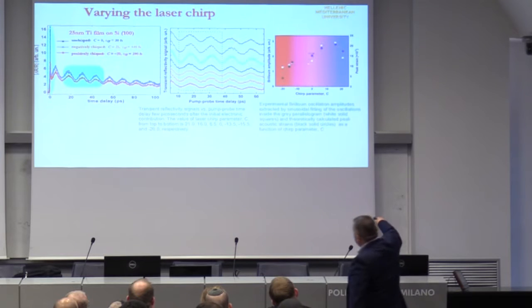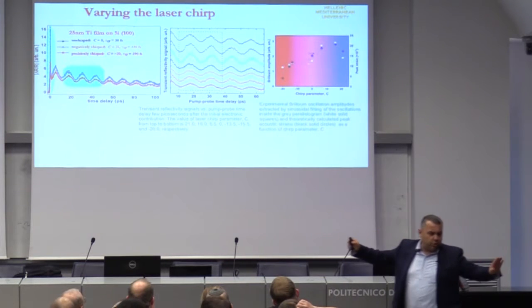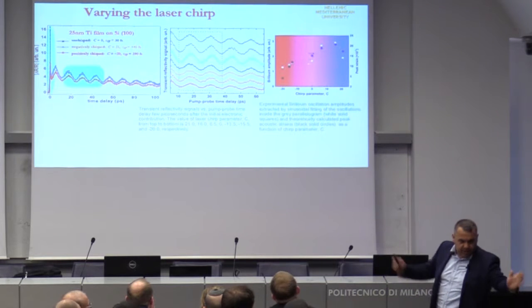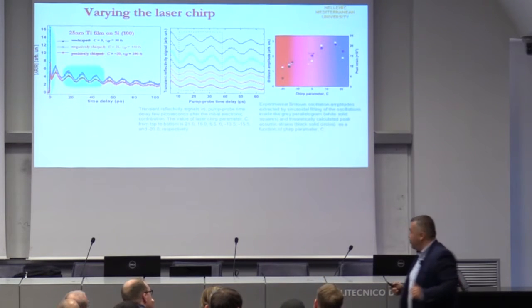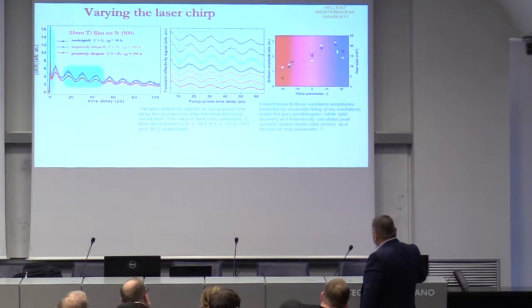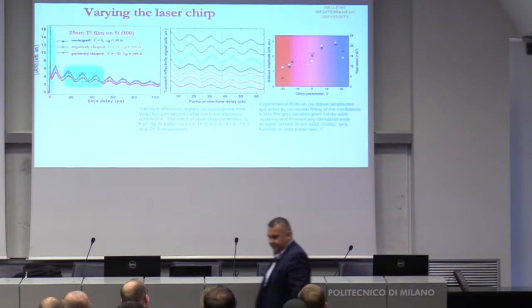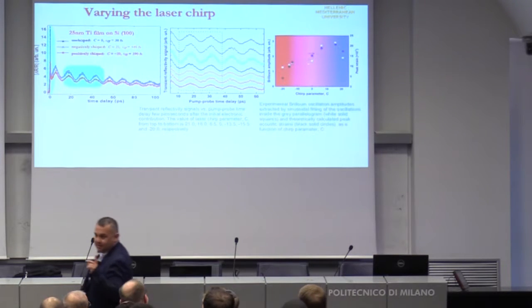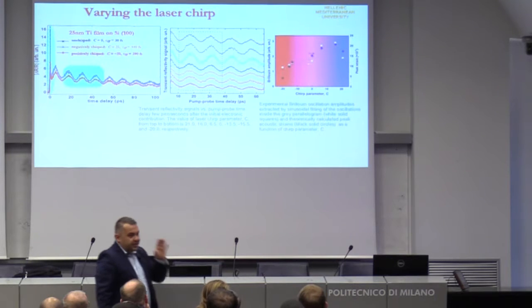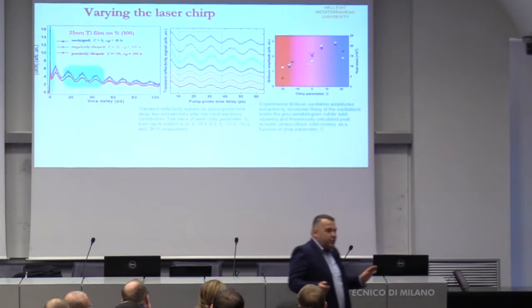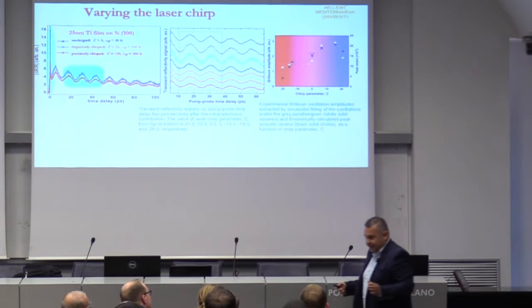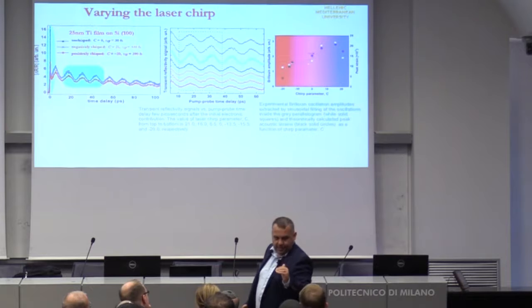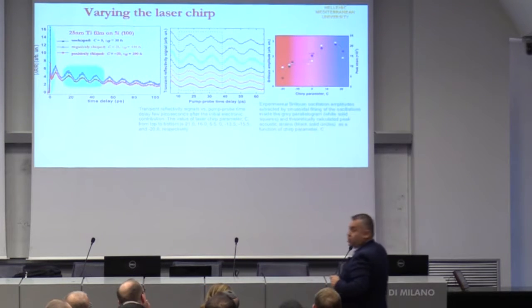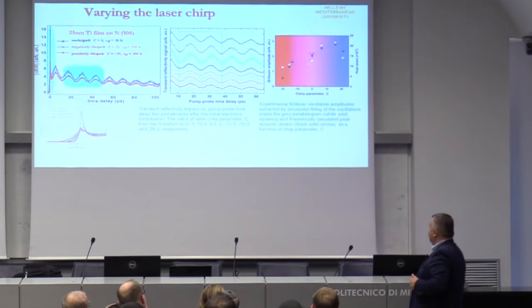If you see the Brillouin amplitude here with the same experimental conditions, we do nothing to the experimental conditions, just change the distance between the gratings in the compressor. We have seen that there is an optimum amplitude of strain oscillation when we have a bit of negative chirp. Not at Fourier limited as expected, but a bit of negative chirp. This is something that my PhD student measured many times because I could not believe it. But it was there every time, even in different materials. Let's try now to explain this kind of behavior.